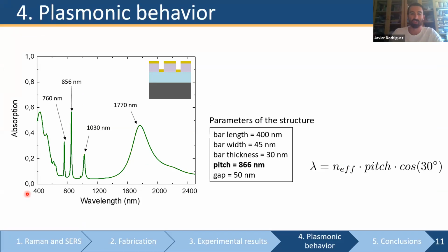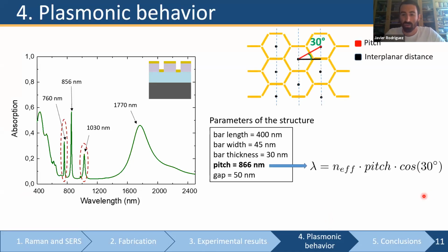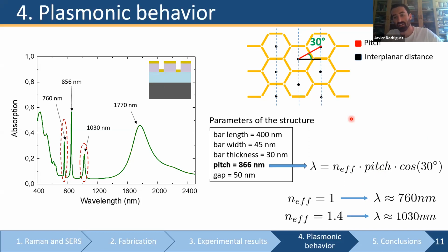If we consider the parameters of the structure, we can see that this honeycomb structure had a pitch of 866 nanometers. So if we remember the diffraction condition for a lattice, we can write it down to be something like this, where we have introduced an effective refractive index to take into account the fact that the bottom structure is embedded in silicon oxide and the top structure is mainly in contact with air. So if we put the numbers here and we take the effective refractive index as 1 for the top structure and 1.4 for the bottom structure, we get exactly the wavelengths at which we are seeing the collective excitations.